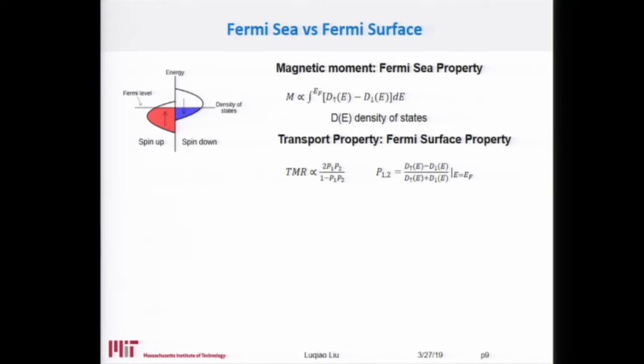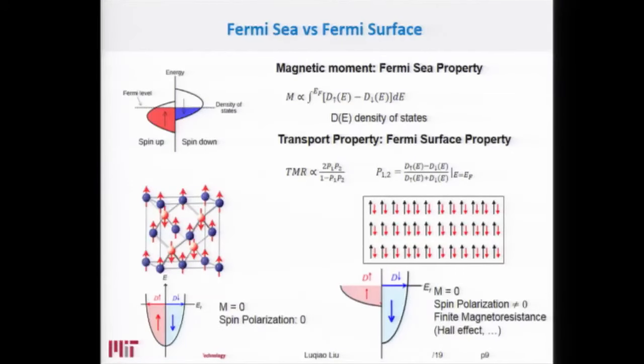Okay, so now knowing this difference, we can potentially design a material system which has zero moment. In order to reach zero moment, you just make sure that the integrated total number of states below the Fermi level are the same between the up and down bands. At the same time, you can still ensure that there is a finite spin polarization at the Fermi level. For example, here, the density of states for spin up is much larger than the density of states for spin down because of this asymmetry.